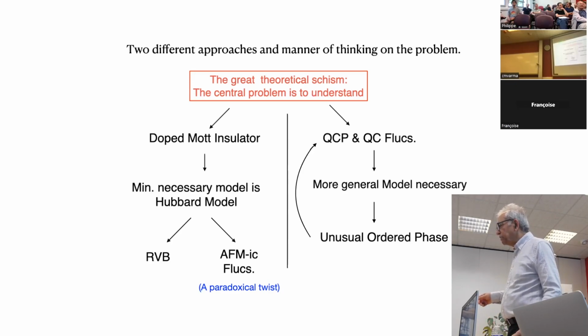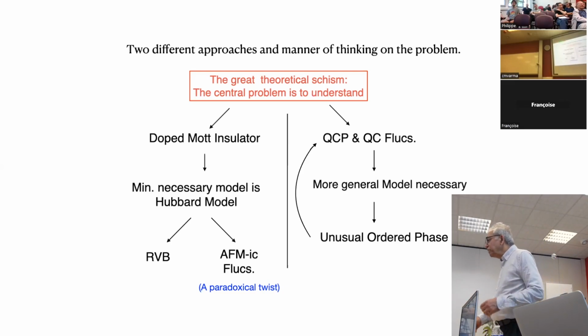And so we are getting attuned to being bombarded with materials which behave linearly with T. And if they have both linear T and T log T entropy, I cannot see any other way than getting the quantum XY. So it's not enough to say that there is a quantum critical point, but to specify the nature of the order parameter and show the fluctuation power of the quantum XY.